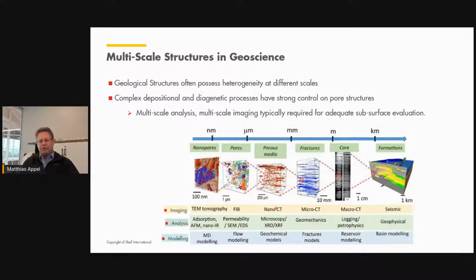Then we are getting into larger structures, where we see connection between our individual pores towards fractures, where the geomechanics element becomes very important. Fracture modeling. Now it could be medical CT or micro CT, probably more micro CT, to see sub-millimeter type fractures. And ultimately, the length scales getting into core, we are working with very different physical measurements, very different uncertainties and challenges for the modeling towards the entire formation, where we're now talking about kilometer length scales. Seismic is kind of the only measurement that we really have there in the subsurface to give the structures. And then the geophysical and basin modeling, where basically geological assumptions about the geology are made to describe these structures.